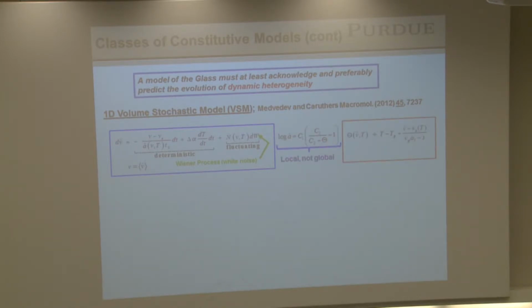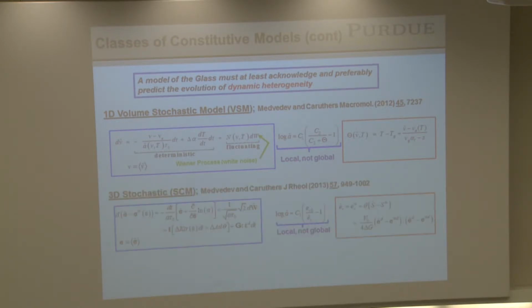So if we do that, all the nonlinearity is again buried in this log A function. This is the functional form. But the key issue is this log A is now local. It is what the instantaneous domain is doing. It's not been averaged out first. So that's the 1D model with Grisha. We made it 3D, and this is all the math that does that. Again, the key issue is this is a local, not global, variable. So I'm not going to put you through the math, but you got the basic idea. What it says is local relaxation depends upon the local state.